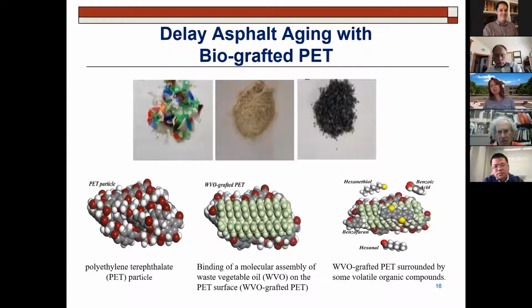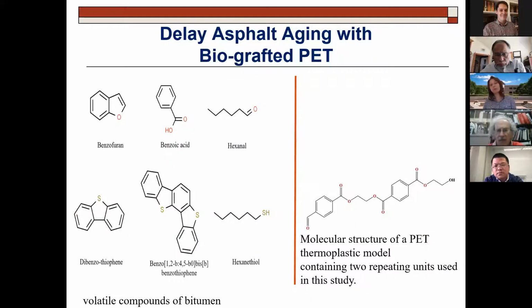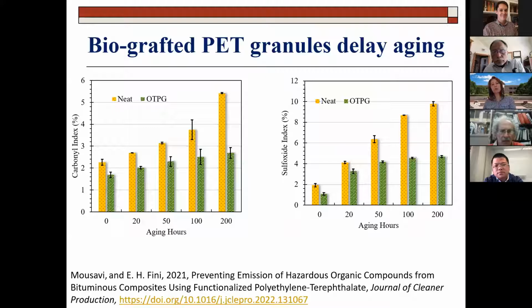The methods of making those plastics are easy. You can follow this paper that we published on plastic. These are mixed plastics made from bottles or shampoo bottles, whatever is mixed. And then we treat them to become this, the middle picture, which is PET grafted by bio-oil. And then it absorbs some of the asphalt molecules, like hexanal and benzoic acid, on the surface of it. This is just a DFT calculation. I'm not going to go too much into the chemistry side, but we show how the biomolecules can actually attract and absorb asphalt molecules. On the left are the asphalt molecules we picked. On the right are the PET plastic molecules that are interacting with asphalt. And this work was published in this paper.